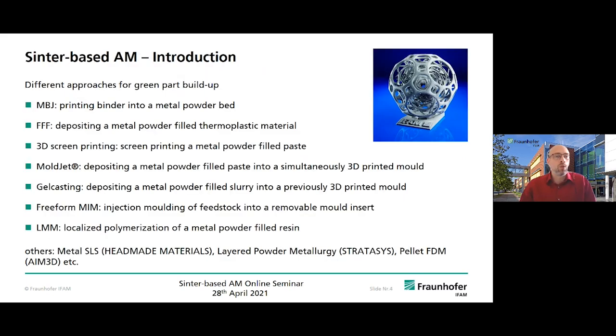And when I just very quickly tell about the different approaches for these processes, as Bastian mentioned, basically the difference is in the green part build-up and the related powders and binder approaches that are suitable, where binder jetting makes use of the free-flowing powder and printing the binder into the bed. The fused filament fabrication deposits a feedstock, basically a thermoplastic material with a high powder load, onto the print bed, the print plate, basically. 3D screen printing makes use of a powder-filled paste, which is pushed through a screen at the spots where the screen has its, let's say, spaces for the paste to fit through.